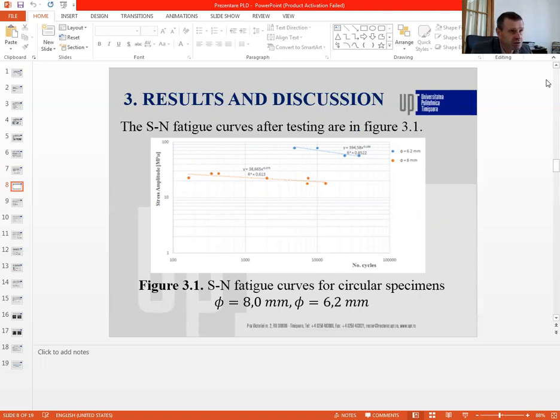The test results are shown in figure 3.1, an S-N fatigue curve corresponding to each set of samples tested, excluding specimens that were broken or showed major casting defects. The tests were performed under similar conditions for the two sets of samples. The results indicate a major effect of section size on finite fatigue durability.